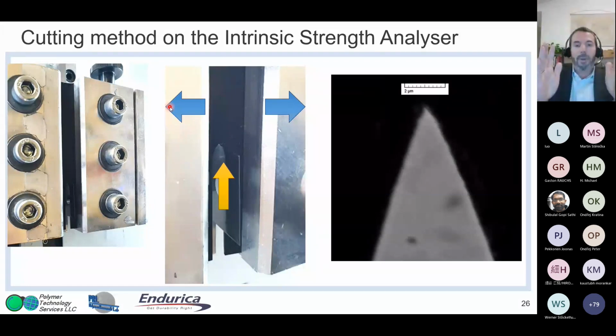Open the crack, right, at some given tearing energy. And then while the crack's open, push a very sharp blade. You can see this is a 2-micron bar here, a very sharp blade, push it into the crack while it's open. And it's not a single measurement. You have to make measurements at several different points.